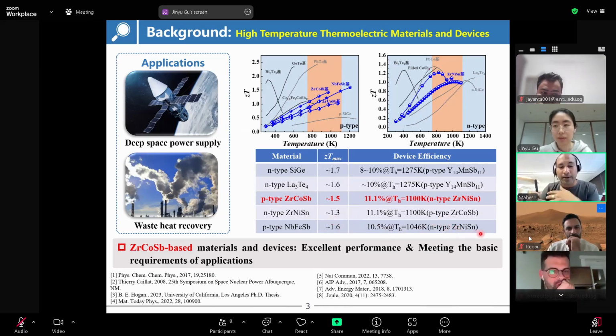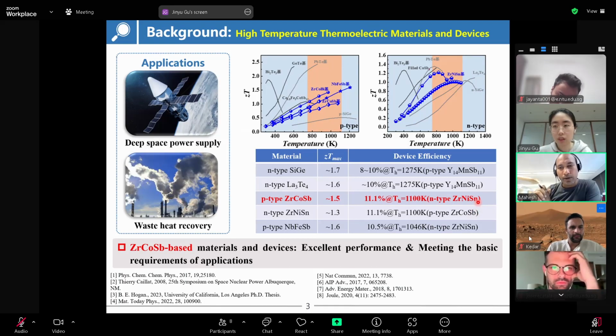You generally intentionally oxidize these legs, right? To avoid further oxidation. Instead of doing further oxidation in sintering at high temperature, can you just coat with some stable thermal oxide on those legs? Will that be helpful, or is this way much better?